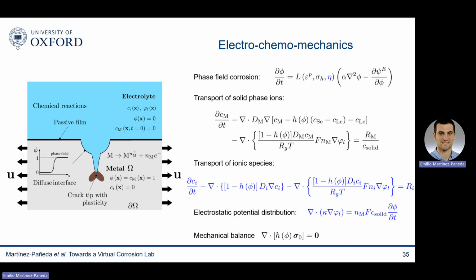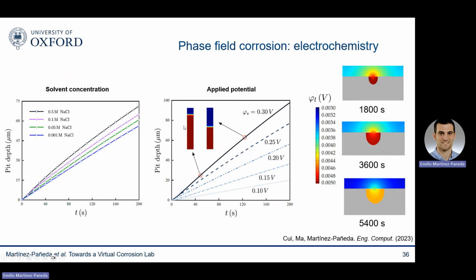Another key ingredient is electrochemistry. We can fully resolve the electrochemical behavior of the electrolyte and capture how it impacts corrosion through changes in conductivity. And you can see here that the model is getting bigger, but again, computers nowadays can handle this. And all the new physics that is being incorporated into this model relies purely on physical parameters. There are no mysterious fitting coefficients nor any strong assumptions. All the mesoscale physics is being resolved. And when you do that, then you can capture the role of solvent concentration, of applied potential, and you can see how the electrochemistry of the electrolyte evolves in time with changes in the corrosion front.